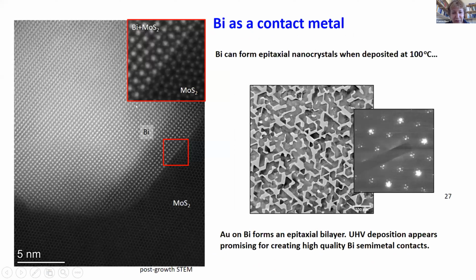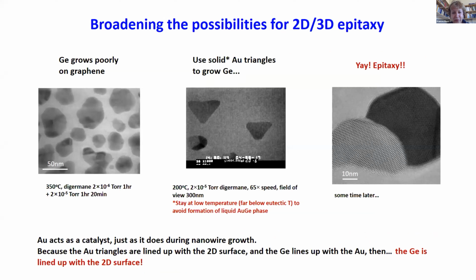Okay, so the last one I'll show you is bismuth, and I'm showing you this mostly because the image is so beautiful. The bismuth is growing epitaxially on MoS2, and you can see how the atoms line up after we deposit bismuth carefully and form an epitaxial, continuous but not complete layer, right? So if we want to broaden the possibilities of this, I've talked about growing metals on 2D materials, but how about we grow some other things?